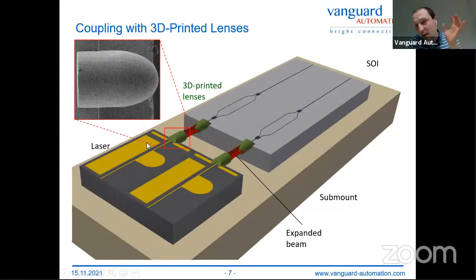Now, with that said, we cannot only print photonic wire bonds, of course. We can print 3D lenses, for example. You can see them here. And our main value proposition is they're reliability tested. So I'm absolutely a polymer person in this polymer glass discussion. That is because we can make polymers reliable. And they have the key advantage that if you print them onto something, they don't shrink. Like we can have Telcordia tests and have shrinkage well below 1%, like 0.5%. So it's really, really accurate.